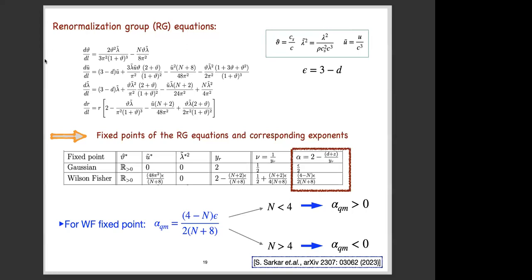What we find is that for the Gaussian fixed point, it is epsilon over 2, where epsilon is basically 3 minus d, that is how far we are away from three dimensions. But for the Wilson-Fisher fixed point, this specific exponent is given by this quantity here. So we have a situation, not for the Gaussian, but for this Wilson-Fisher fixed point, where if we consider n to be less than 4, we can have alpha quantum greater than 0. And if one has n greater than 4, you can have alpha quantum become negative.